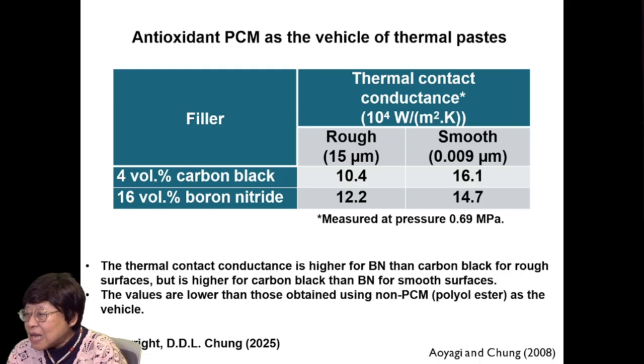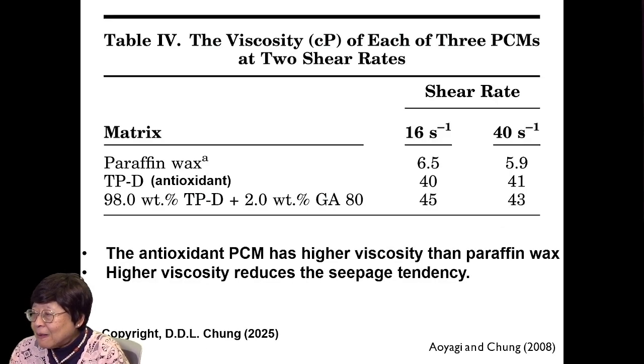The conductance is higher for boron nitride than carbon black for rough surfaces, but is higher for carbon black than boron nitride for smooth surfaces. The values are lower than those obtained using non-PCM (polyol ester) as the vehicle. Okay, so the PCM performance in terms of the thermal contact conductance is not that great. Shown here is the viscosity of 3 PCMs at 2 shear rates. The antioxidant PCM, which is the bottom row, has higher viscosity than the paraffin wax, which is the upper row. The high viscosity reduces the seepage tendency.